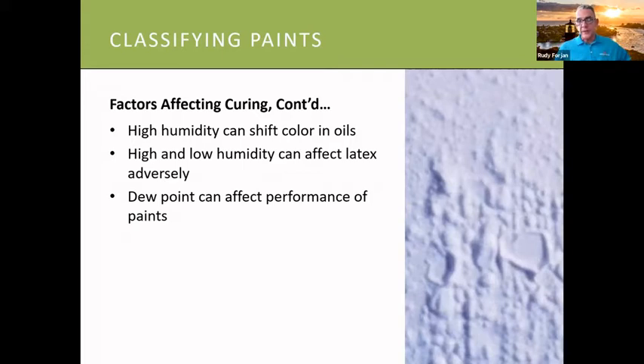Dew point is a real big piece that we have to deal with down in South Florida. When we talk about dew point, we're talking about the temperature of the air being lower than the dew point of the substrate. In other words, the presence of moisture will affect adhesion. For instance, if you fill up a glass of water and put some ice in it, the sweating that you get on the outside of it, if you get that kind of sweating on coatings, it can affect adhesion, it can affect dry time, color, and especially with oil-based paints, it can affect gloss itself. It happens with both coatings. Essentially down here, we have 2 periods of the year where we have the biggest issue with that. That generally is in the spring and the fall, when we see a lot of dew on our cars in the morning or on bushes and everything around us.